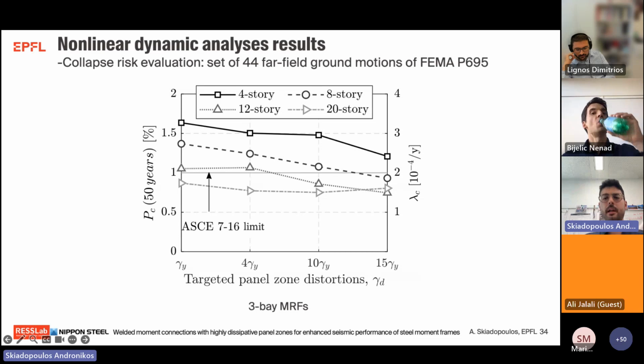Nonlinear dynamic analyses were conducted for all 32 steel buildings based on the 44 far-field ground motions of FEMA. What we see in this slide is the probability of collapse of the moment resisting frames over 50 years on the vertical axis, and on the horizontal axis, the targeted panel zone shear distortions of 1, 4, 10, and 15 gamma y.